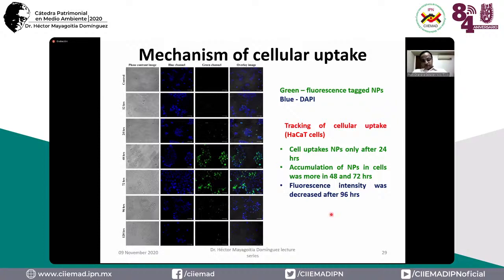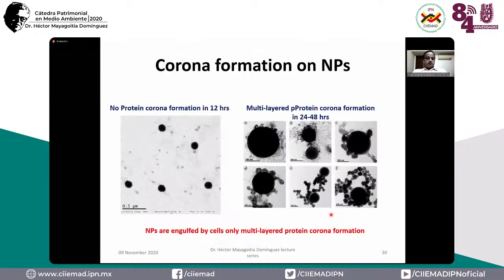Then what is happening after that? The corona formation on nanoplastics. This is what is happening. Slowly the corona started to build up after 24 to 48 hours. Then after 24 hours, these plastics got engulfed into the cell system. So nanoplastics are engulfed by cells only after multi-layered protein corona formation, because before that the cell was not able to recognize them as a self material.